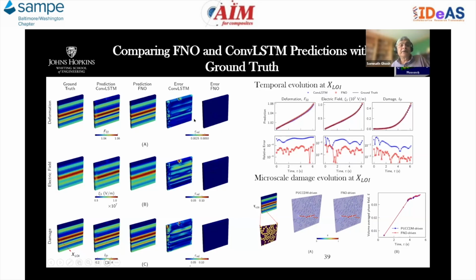For the ConvLSTM, there are significant errors, particularly near the surface, because of the sparse surface measurements. On the other hand, because we are mapping between infinite spaces for the FNO, in this case, the error is very small. And here you can see a comparison of the relative error as a function of time at a given location of interest. The blue one here corresponds to the ConvLSTM. The red one here corresponds to the FNO.